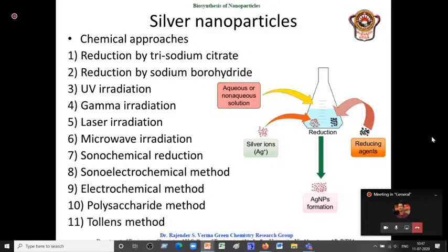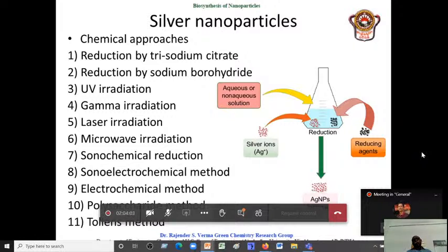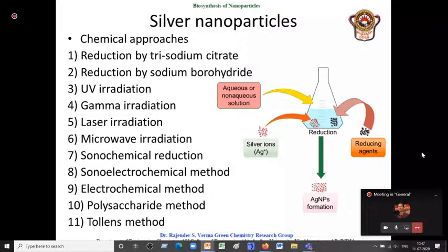We have something like Tollens reagent, which many of the students at the degree level, whenever they do the silver mirror test, ammoniacal silver nitrate, they simply add Tollens reagent, and then they do it. They do the Tollens test. They do the Fehling's test. In both these particular components, even though they do a test and then they see a silver mirror or a copper oxide red precipitate in Fehling's test, they only stop there at that point of how that has been formed. But what actually they have done in that test is they have prepared copper oxide nanoparticles in Fehling's test or in Tollens test.